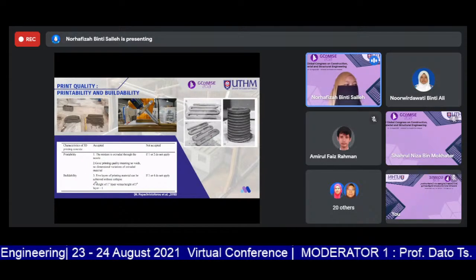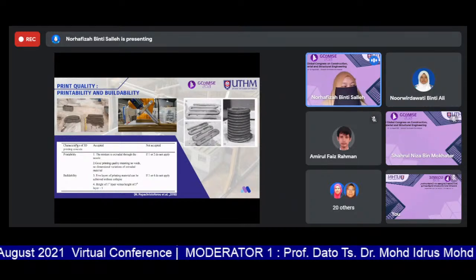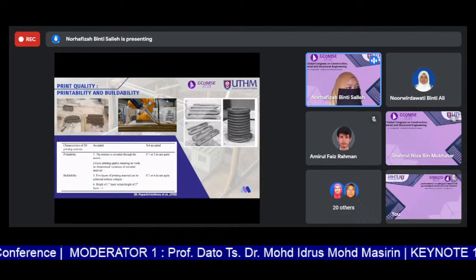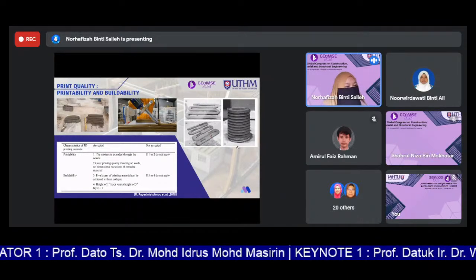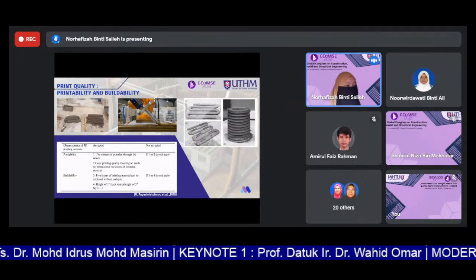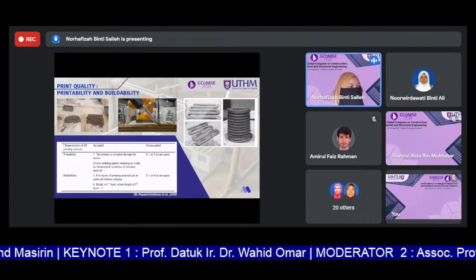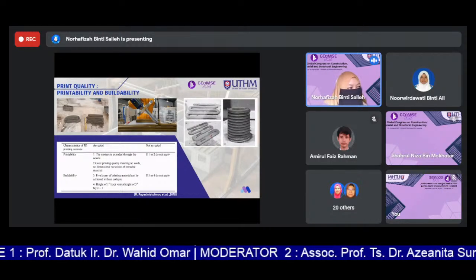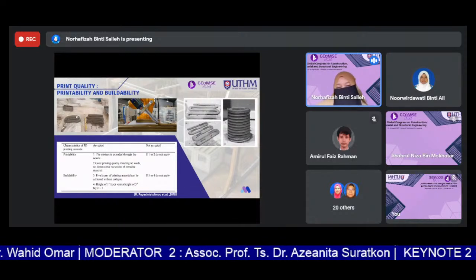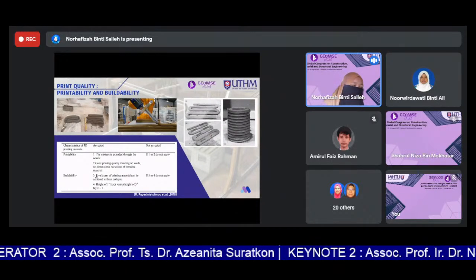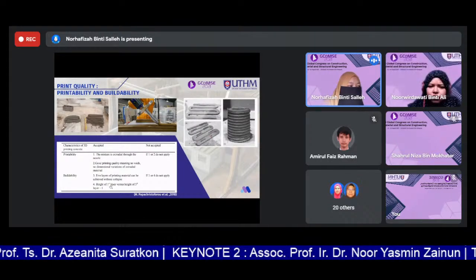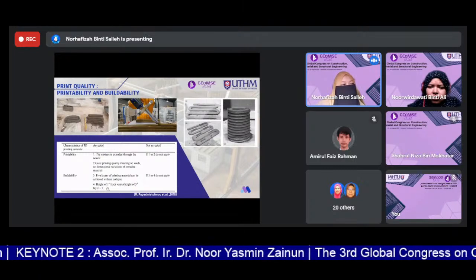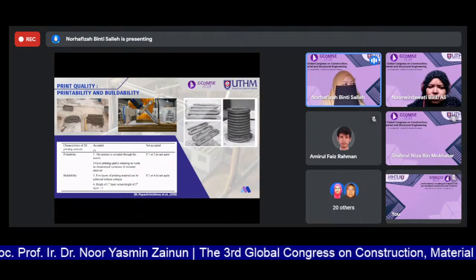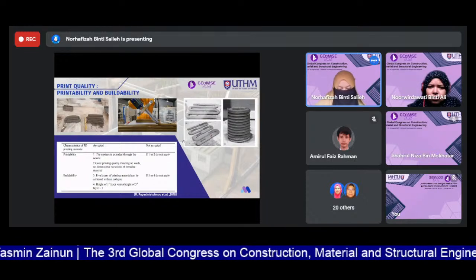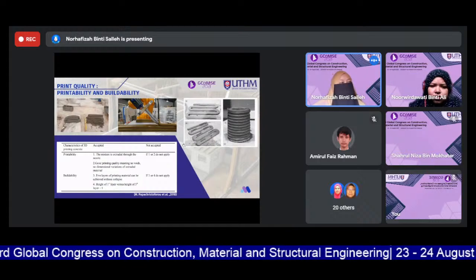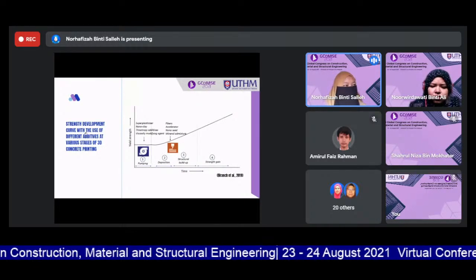Okay, and then buildability. For buildability, 5 layers of printing material can be achieved without collapse. So we must make sure we can layer the concrete 5 layers without collapse. Here you can see we have 2 specimens. The first specimen has 5 layers, but the layers collapsed, so this specimen cannot be used for 3D concrete printing. For buildability, the first item is that the height of the first layer versus the height of 5 layers must be equal to 1. This is a guideline for how to measure the printability and buildability of 3D concrete printing.